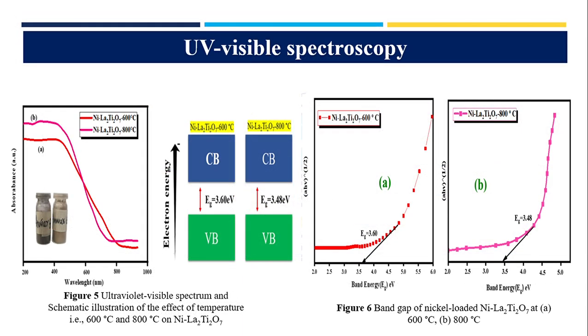After this, I will explain the UV visible spectroscopy. It is also an important characterization technique used to study the optical properties of the material. The absorption spectra and the values of the band gap are given in the figure. As we can see, the value of the band gap decreases as the temperature increases, which means the relation between band gap and temperature is inverse. The band gap of the nickel loaded lanthanum titanate calcinated at 600 degrees Celsius is 3.6 electron volt, and the second band gap value is 3.48 electron volt.